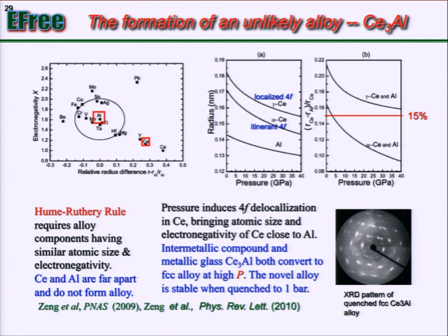Initially we studied the cerium aluminum metallic glass. Metallic glass is a relatively new material, which is very useful for structure because, unlike regular metal, which is crystalline, has cleavage and will break at some crystal boundary, a glass does not have a boundary, so it's all continuous, and so it has better mechanical properties in some sense. Recently it has been well developed. In the past it was difficult to make such a thing, but now with very fast quenching, you can make films or even bulk samples of metallic glass.